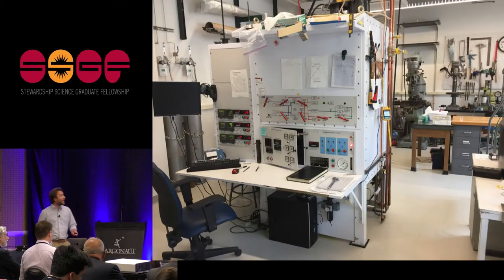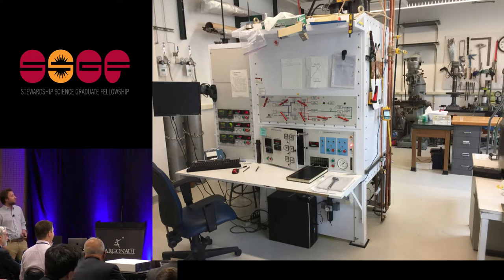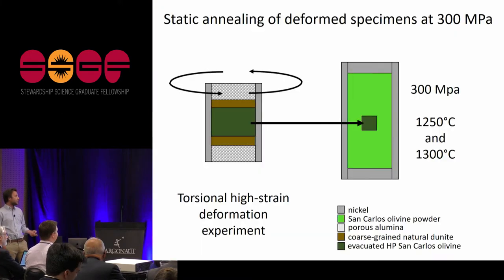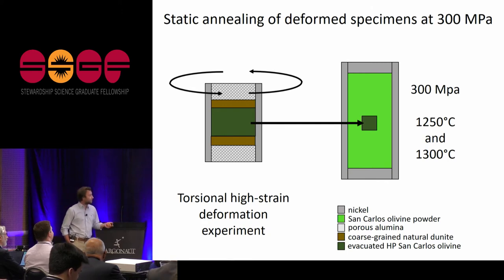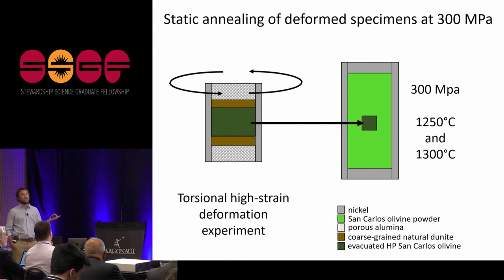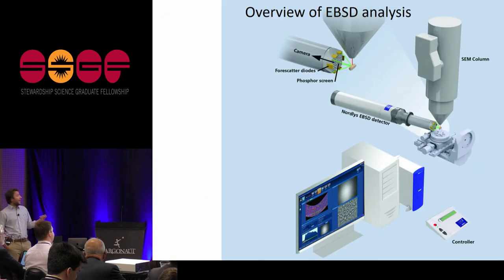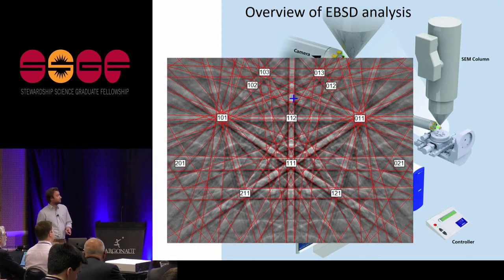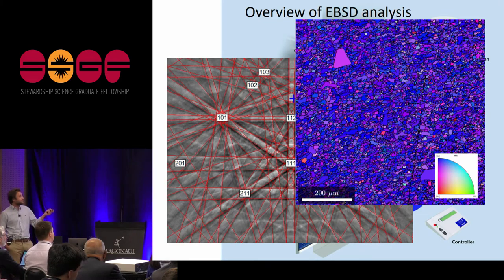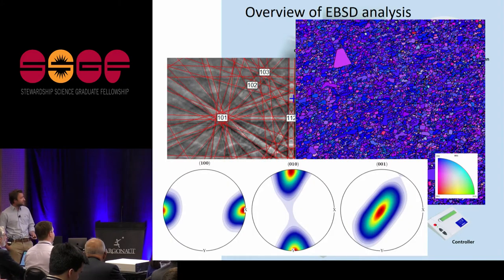Here's a picture from the lab — that's the seat I spent way too much time in front of, next to our internally heated pressure vessel deformation apparatus. We then study microstructural modification under static conditions after deformation: the deformed sample is cut into pieces, placed back inside powder, and annealed. After the experiment, we do EBSD — examining Kikuchi patterns to determine crystal orientations — then create false-color maps of crystallographic orientation and examine the distribution of crystallographic axes in the rock.